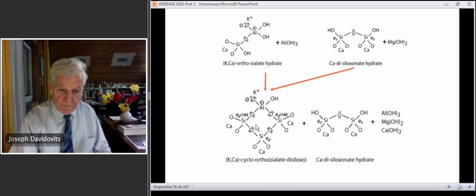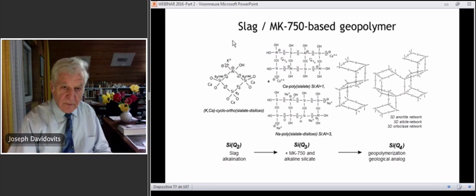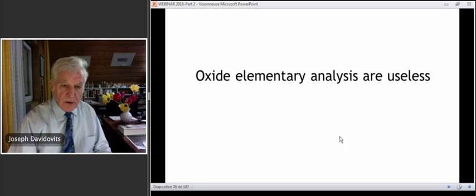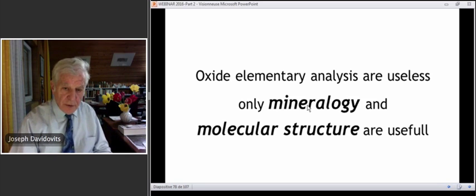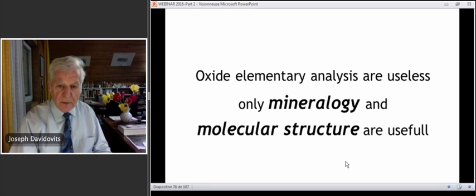If you stop here, this is what you get: a mixture of this small molecule and CSH, plus aluminum hydroxide, magnesium hydroxide, and calcium hydroxide that are precipitating. For slag MK-750 based geopolymer cement, they polycondense with metakaolin and form the first step, the ribbon, the calcium polysialate, and the sodium or potassium polysialate, that further polycondense into a three-dimensional network. So the oxide elementary analyses are useless in terms of understanding what is going on in geopolymerization. Only mineralogy and molecular structure are useful, but nobody cares about this. This is why people don't understand what is going on.